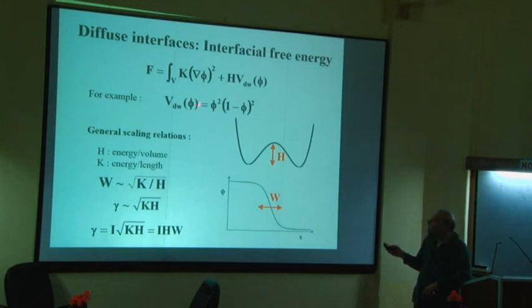Here I've taken w like Guru did yesterday, with equilibrium values of the phase field equal to 0 and 1. And then we have seen, and you have found in your tutorials, that we can find the interface thickness and the surface tension by combinations of these two coefficients.